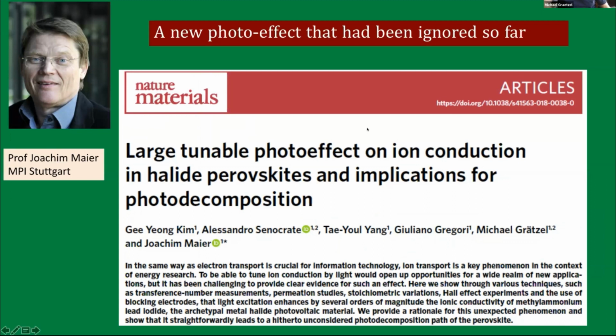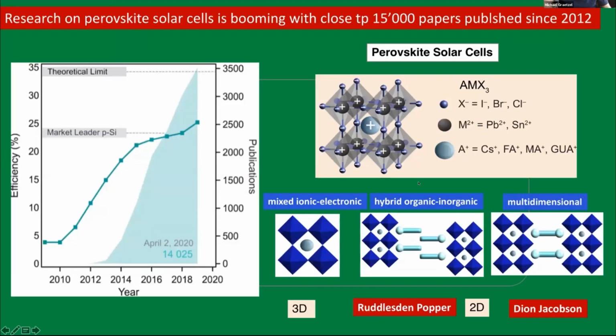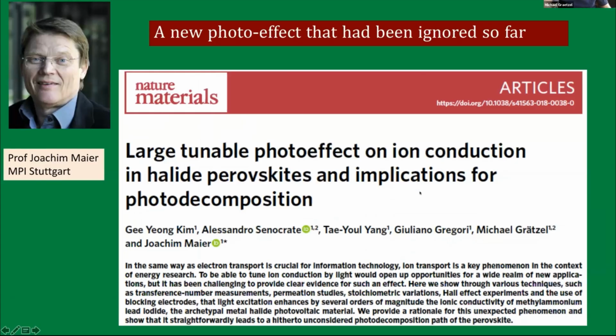And just to mention the photo effect on ion conduction. That was totally unexpected and came out of the blue. And it was actually Joachim Maier. We collaborated with him. He's a director at the Max Planck Institute in Stuttgart. And I'm actually an external member of the same Max Planck Institute. And so we had a long-term collaboration with him. And he discovered that the ionic conductivity of these materials went up 100 times, several hundred times under light. And that was quite a shock to the community.